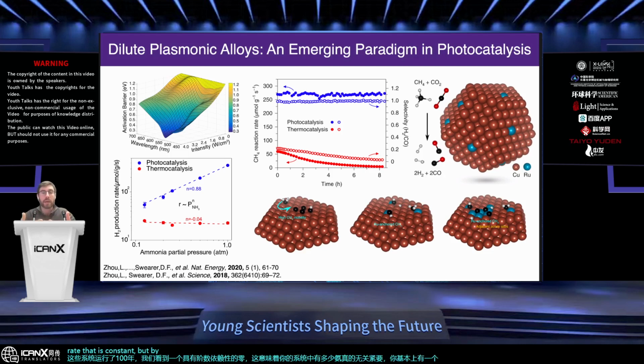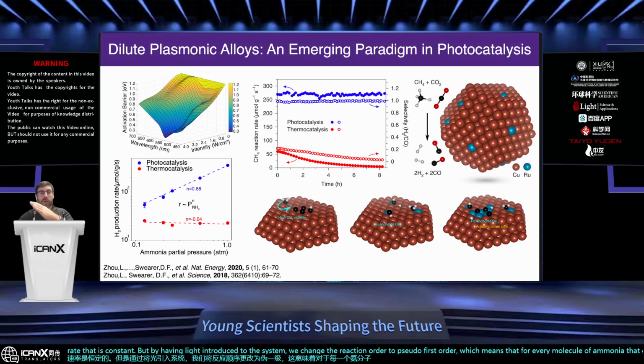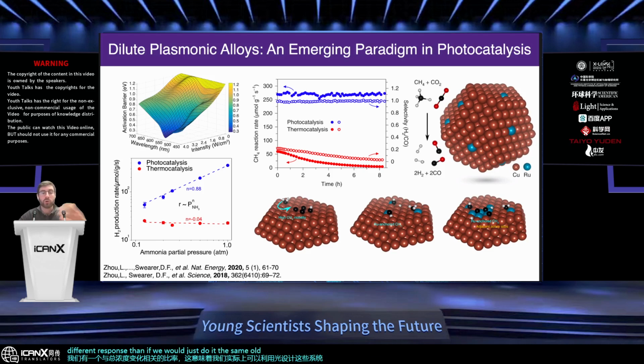But by having light introduced to the system, we change the reaction order to pseudo first order, which means that for every molecule of ammonia that comes in, we have a rate that's associated with that change of the total concentration, which means that we could actually engineer these systems using light to have a completely different response than if we would just do it the same old, same old. So photonic energy can really, really make a big difference.